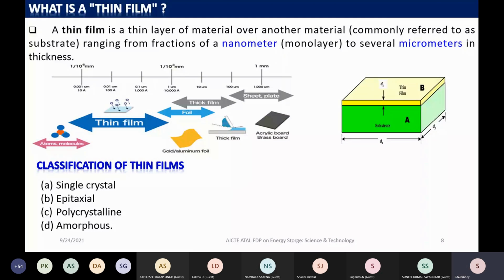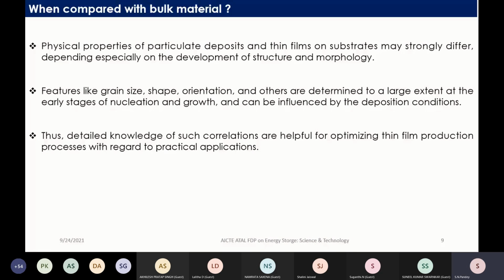Now come back again: if we compare with the bulk material, the physical properties of the particulate deposits and thin films on substrates may strongly differ, depending especially on the development of structure and morphology. When you are depositing a thin film, its structure depends on how you are depositing it, which method we are using, and the structure and morphology change. Features like grain size, shape, orientation and others are determined to a large extent at the early stage of nucleation and growth and can be influenced by the deposition condition. So that is very important.